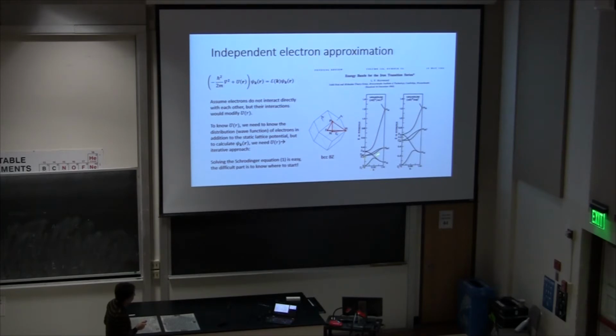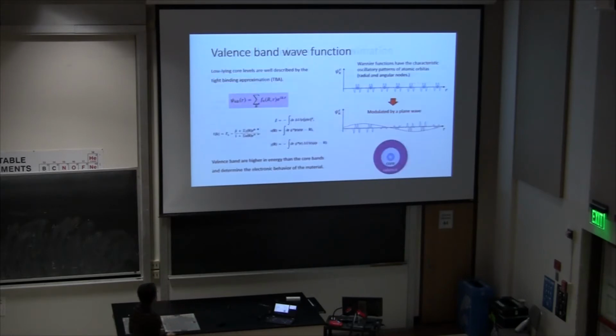Let's look at this distinct feature right here in the middle. You have the same thing here, right? And the splitting over here, you have kind of the same thing here. The splitting here, you have almost the same thing here. So overall, they look similar, but the actual energies are quite different between these two calculations for the same element. This is just an element, right? And then you have to pick which one is correct and which one is not. You can imagine that if you go beyond elements, just your starting point can take you to very, very different solutions. So, okay.